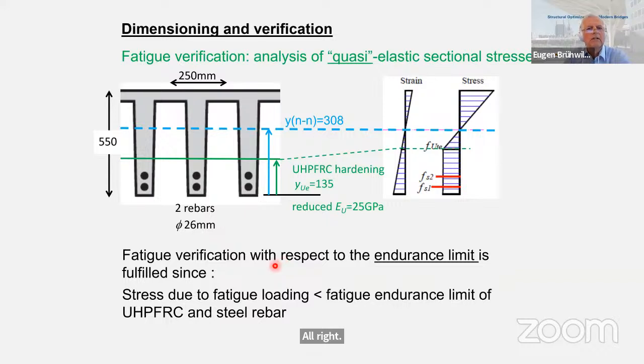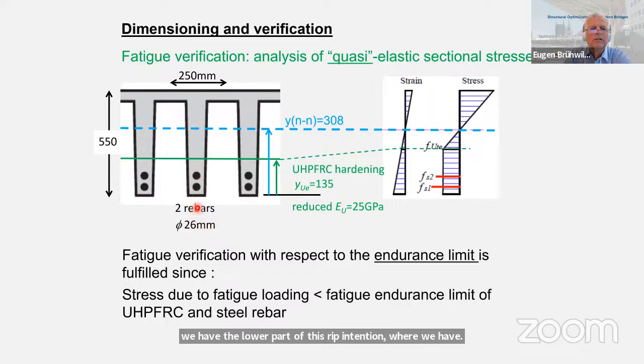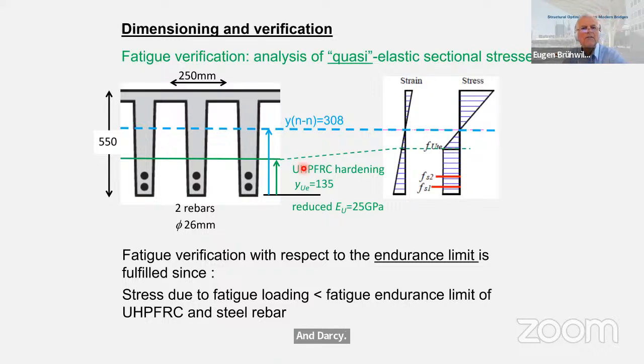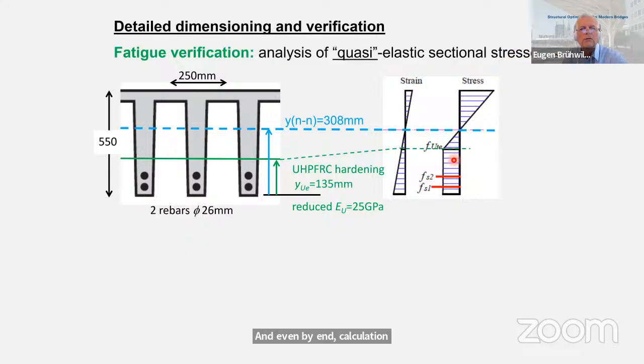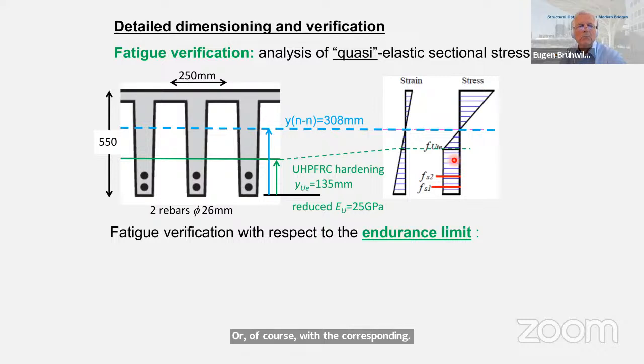Now, with respect to the fatigue, very important. So we have the lower part of this rib in tension, where we have the 2 rebars in this case, rather thick rebars. They are in tension, of course, and also the UHPFRC material. It is, however, in the strain hardening domain, and thus it loses its stiffness a little bit, this lower part, and we have to find the strain, and in particular the stress distribution of this type in the cross-section by iteration. But this can be done even by hand calculation, or of course with the corresponding cross-sectional numerical model.